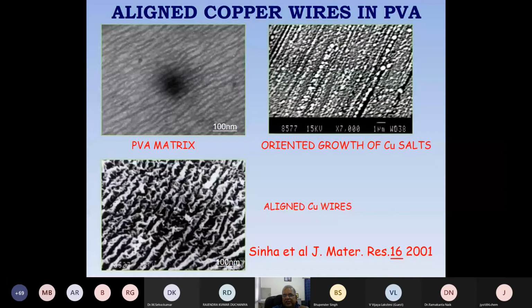I will show you. This was one of our very first experiments where we dissolved PVA of a known average molecular weight and a known concentration into water, and then allowed it to form a gel at room temperature by physical cross-linking. We have not used any cross-linker; in none of our experiments have we used any cross-linker. Once the gel was formed, we put it under vacuum to dehydrate it. Once it got dehydrated, we put it under the electron microscope, and we found that there is a parallel arrangement of the PVA tubules. You can see here.